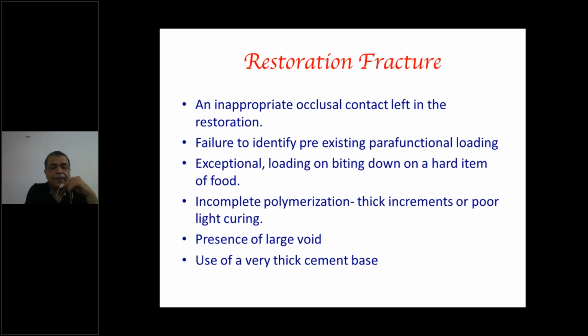The restoration can fracture. As you see in the last slide also, the problem in the post-operative sensitivity is not a problem of the composite, but the technique and how we use them. Same way for the restoration fracture, if you have left an inappropriate occlusal contact in the restoration, or you have failed to check for any existing parafunctional loading, or the patient has bitten on hard food, it can lead to restoration fracture. Or if you have incomplete polymerization, where you have used thick increments or your light curing unit was poor, that can lead to restoration fracture. Or if there was a presence of a large void, or you have used a cement base like glass ionomer, this can also lead to restoration fracture. So again, most of the reasons here are dentist based and patient based, and not material based.